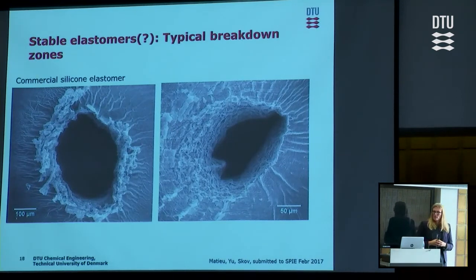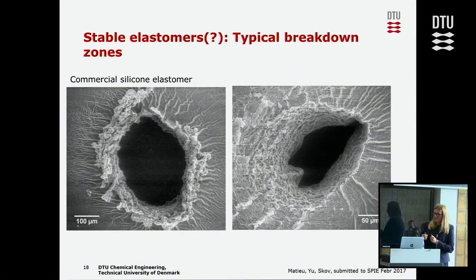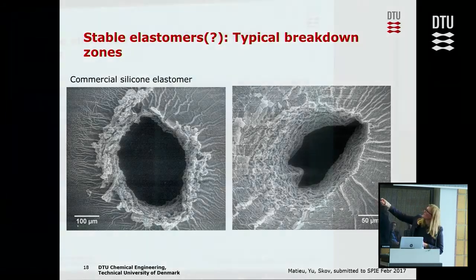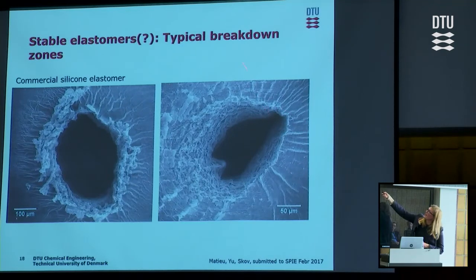Stable elastomers, of course, shouldn't break down electrically or mechanically, but usually the problem for dielectric elastomers is a mechanical or coupled electromechanical breakdown. But when we look into the large products where we have a lot of films assembled into products, then the problem is actually an electrical breakdown that burns a hole in the film. But then usually when we have our material, we will have a mechanical stress over the material, and we will see a stress propagating from this area through more or less the entire product, and then the product will fail. So all these residual stresses are actually solidified areas, and then we of course have a huge stress gradient between these threads and the silicone matrix, and here we will see the crack formation happening.